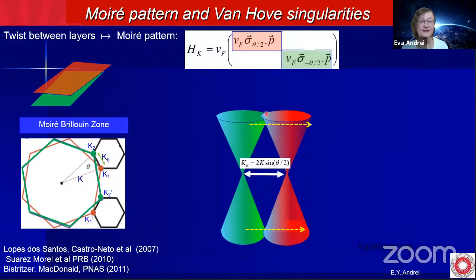So now if we look at these 2 cones, let's say that belong to the K valleys of the top layer and the bottom layer, you see that there's an energy at which they cross each other. The distance between the cones here in K space is just proportional to the twist angle. So this is our Hamiltonian, the Hamiltonian for the K valley, just in this Brillouin zone for the top layer and the bottom layer.